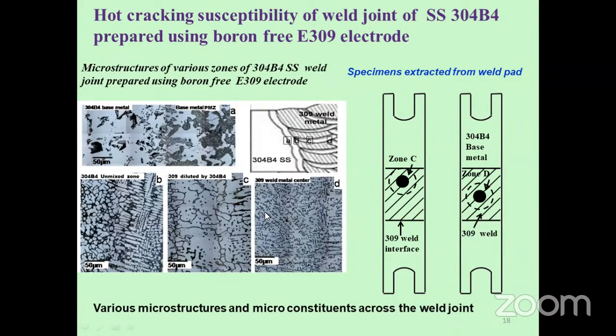And far away from this zone is the region C, where it is interior to the weld metal, almost the center. We see only the austenite dendrites and the interdendritic delta ferrite. This is a microstructure. Here it does not contain any boron from the base metal. So this is a basic microstructure. So here we can see that this weld metal diluted by the base metal is more vulnerable